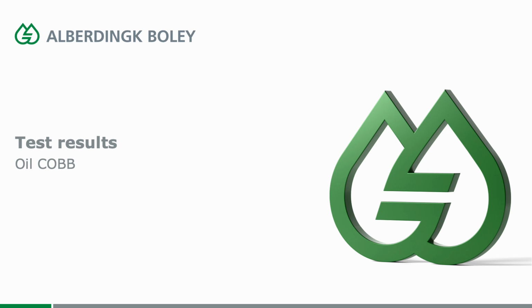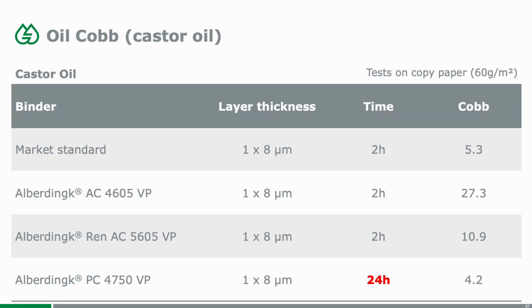To carry on with resistance to oils and fat, we also make oil COBB. And in case of the oil COBB, we are using castor oil, and again the test is done on copy paper. 8 microns wet application. You can see that the market standard and the AC 4605 and the REN AC 5605, they all have been tested for 2 hours, and the results are, I would say, pretty good.